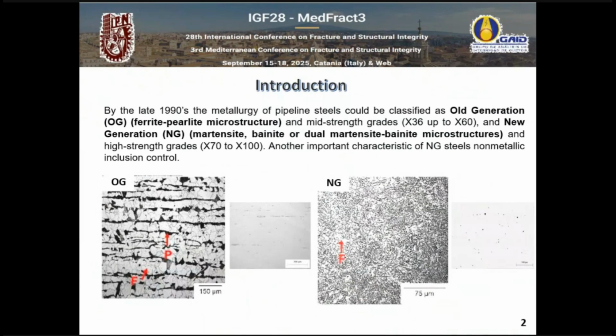And these new steels are basically high-strength low alloy. That means they have been treated with vanadium and calcium and some other rare earth elements to produce an ultra-fine grain microstructure, and they also modify the shape of the inclusions to be round ones, because in the first investigations of HIC, they realized that these elongated inclusions were the nuclei for HIC.